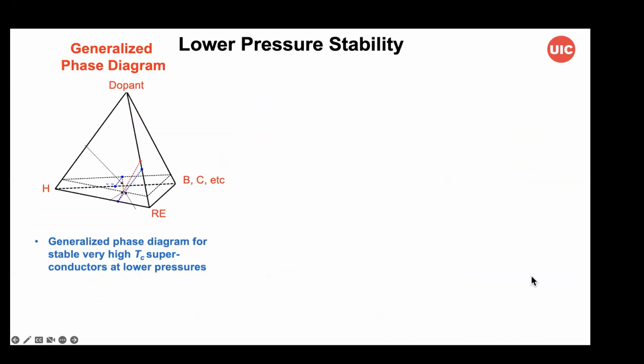So now I just want to turn to the question of low pressure stability in the last couple of minutes. This is a generalized phase diagram that motivates the thinking for doing a lot of this work in taking these interesting phases and looking for analog phases or stabilizing them to lower pressure, where we might have a dopant, we might have elements such as boron and carbon that could be structural elements that would preserve the kinetic or even thermodynamic stability of the system, some kind of heavier element that might provide the electrons to keep the hydride component in a monatomic state as well.